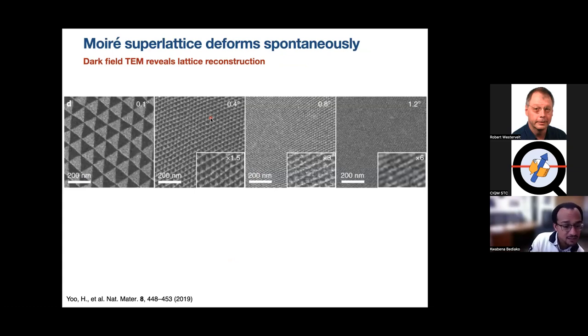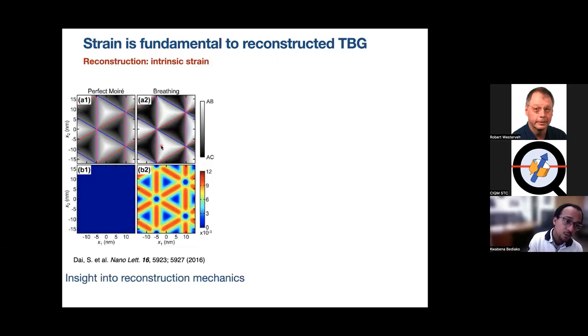Dark field TEM, again, this is Hyobin and Rebecca's work, had shown that this lattice relaxation is indeed taking place, particularly clear at small angles. And so one of the outstanding questions that we had was, can we measure experimentally the exact amounts of these rotations, and what might we learn from that if we could do such an experiment? Our approach to accessing these quantitative measurements of the relaxation was to measure strain, because it turns out that